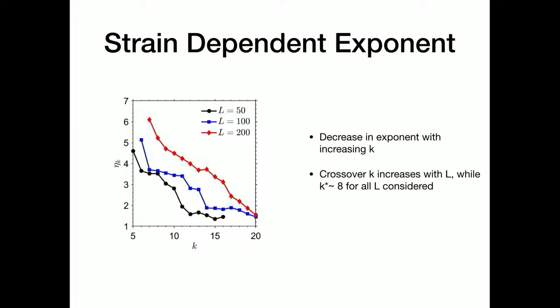In contrast, K star is, we saw earlier, quite insensitive to system size, so the warning about imminent failure if you are using K star is significantly earlier.